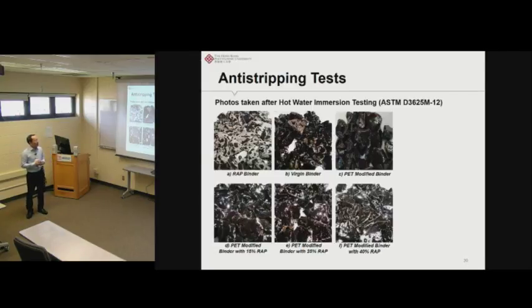So first is the anti-stripping test. The anti-stripping test we have conducted is the hot water immersion test according to the ASTM standard. I assume probably many of you are familiar with this test. Basically, we first coat the aggregate with the binder, and then we put it into hot water and boil the aggregate with the binder for a certain amount of time, and then we take it out to check the surface coating of the aggregate.